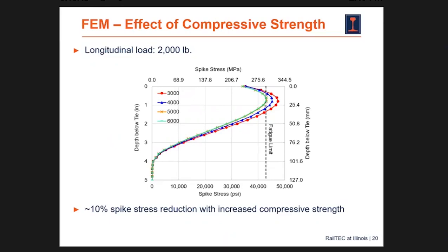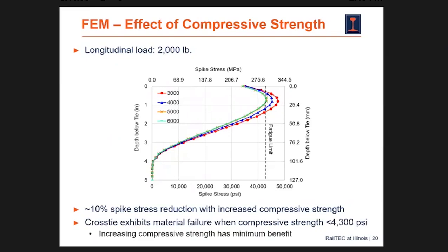But one thing to notice is once you get above, it actually happens to be about 4,300 PSI in this case. Once you get above that, there's no benefit. It doesn't matter if it's 5,000 PSI or 6,000 PSI, you're not gaining any benefit. So there's no reason to actually go up to that high of strength if this is the problem you're trying to solve, which is good information to know.